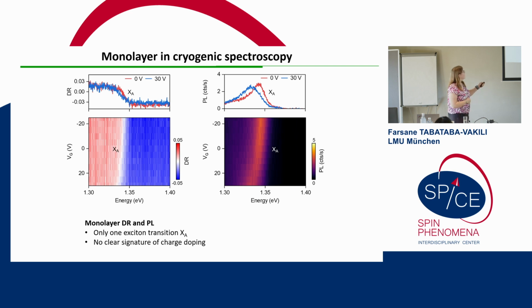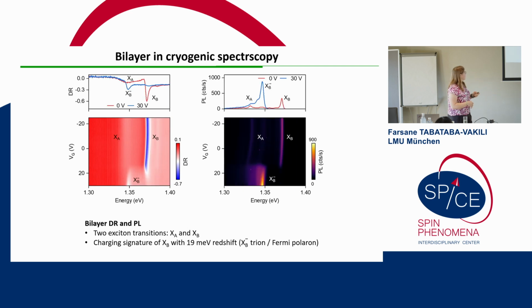And as we apply a gate voltage, we just observe a very small redshift of XA. So no clear signs of charge doping. And we have basically no Stokes shift, so this looks like it is a direct excitonic transition. Then, moving to the bilayer, things get more interesting. In the bilayer, we also see this XA feature at roughly the same energy.